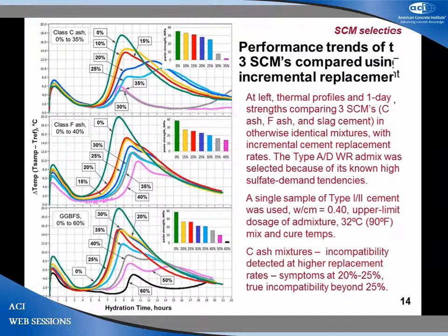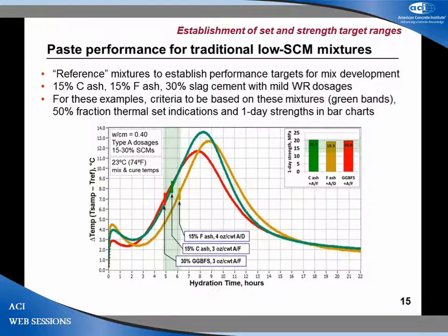The first stage of such a process that we would suggest is to take the traditional mix designs that we're used to, and that might be a 15 or 20% fly ash mix with a mild lignin-based water reducer or something like that, and to establish the trends for both early age strength and age thermal profile setting indication. And so to do that, we've taken three such mixes. We've established a setting time band there. You see the little shaded band. And the same thing in the one-day strengths, a setting time or a strength objective, if you will, for our design mix to be designed.